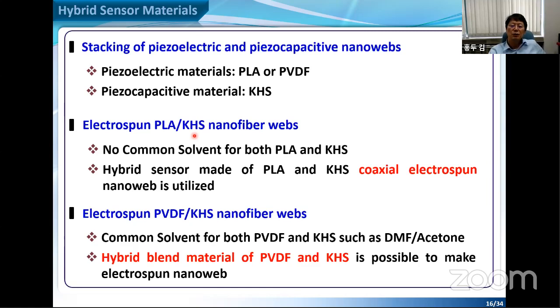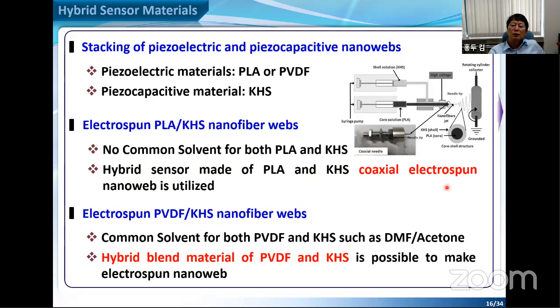So in this case, we use a coaxial electrospin so that we can have both solutions in one nozzle, a core-shell type system, so that in the end we have a PLA core and KHS as the shell. So we tried this second method. The third method is just PVDF and KHS. Fortunately, we found a common solvent, a DMF-acetone system, so using this common solvent we can blend PVDF and KHS with different compositions, so that we can measure the differences between these three different types.